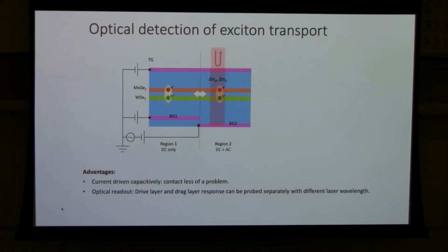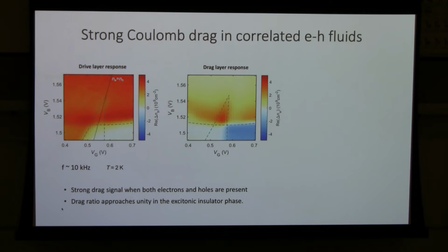As you can see here, we use a modulated backgate, which is close to the hole layer. So if the electron and hole are not coupled too strongly, we can think we are mostly gating the hole layer, so we can call the hole current the drive current. And the electron one, you can think of as a drag current type of thing. So first, let's consider the hole current. What we can see is as long as the system is hole doped, you actually have very strong gate-induced hole current.